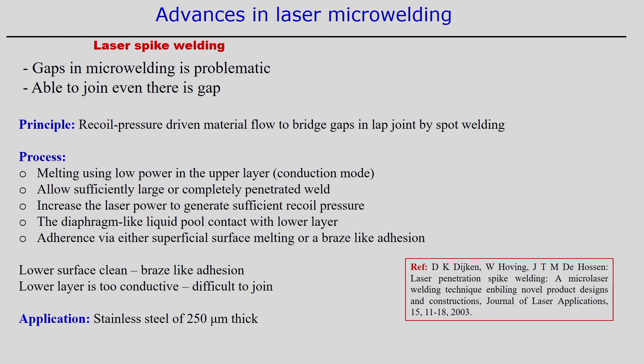Either superficial surface melting or a braze-like addition can be achieved, similar in principle to brazing. This braze-like join is possible using the laser spike welding process. However, if the surface of the lower layer is not clean enough, or if the lower layer is too thermally conductive, heat will be conducted away and joining becomes very difficult. These are the two main issues associated with this process. A typical application is stainless steel of 250 micrometer thickness in a lap joint configuration, joined using laser spike welding.